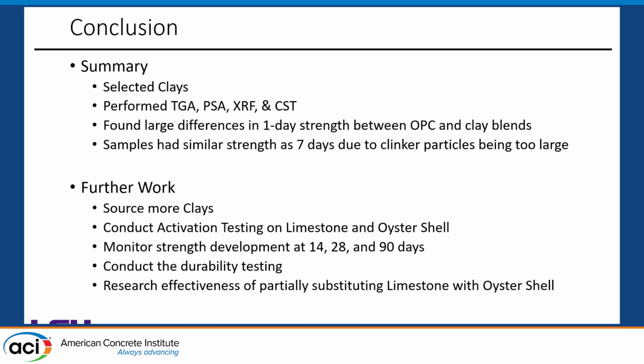In conclusion, just a summary of the work that we conducted. We selected clays from across Louisiana. We performed TGA, particle size distribution, X-ray fluorescence tests, and compressive strength tests. We found a large difference in the 1-day compression strengths between the OPC and the clay blends. However, as time progressed, we noticed that that gap narrowed.